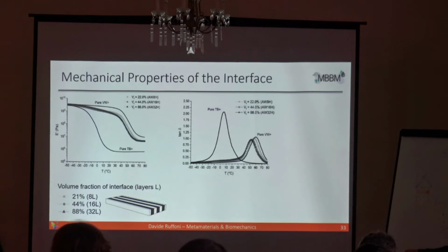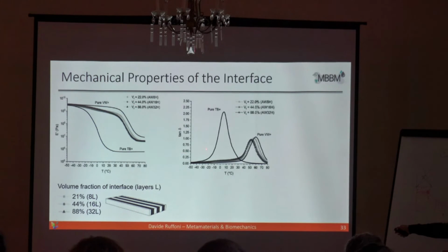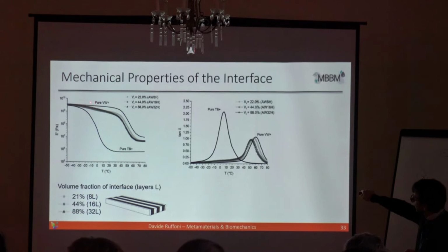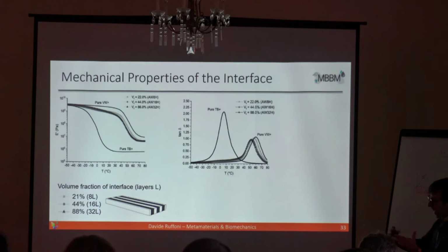Then we considered samples of very different numbers of layers, so 8 layers, 16 layers, 32 layers, and in this case, if we have a blurred interface and we have 32 layers, this is basically a material composed only of interface material. And when we do our dynamic analysis, you see, for example, here the behavior of the pure stiff component, this is the behavior of the pure soft component, and in the transition temperature, in the tan delta, what you see is that when you have a blending of the two materials, the interface behavior is very close to the behavior of the stiff component.